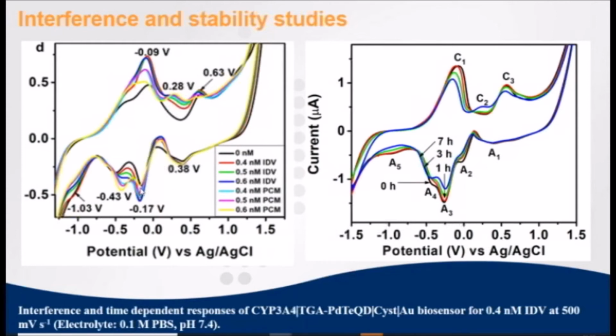After doing the interference study, you can move on and continue with real sample studies. In this case, we employed human serum. We also did a stability study, because after doing the interference, you need to prove that you have developed a sensor for your ARV drug, and then you need to check how stable it is, because most of the time these enzymes denature. So we monitored the stability of the enzyme, and we could see that our biosensor was stable.